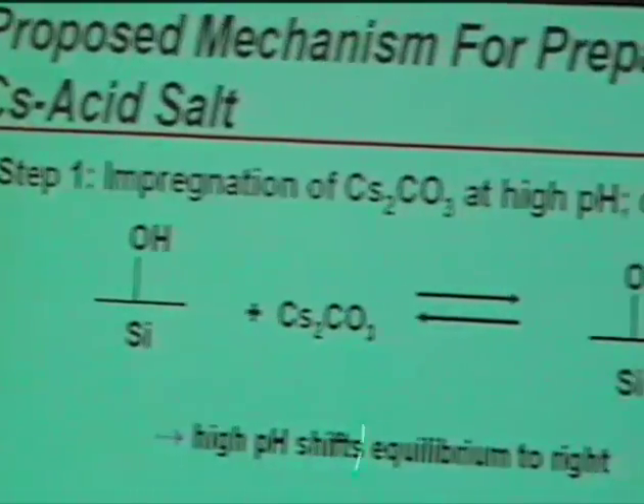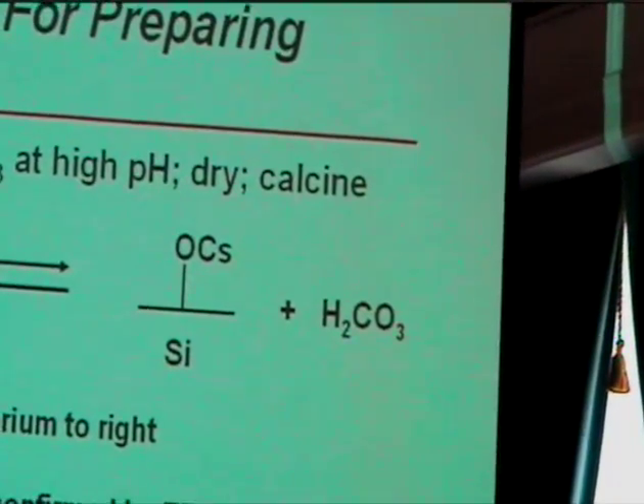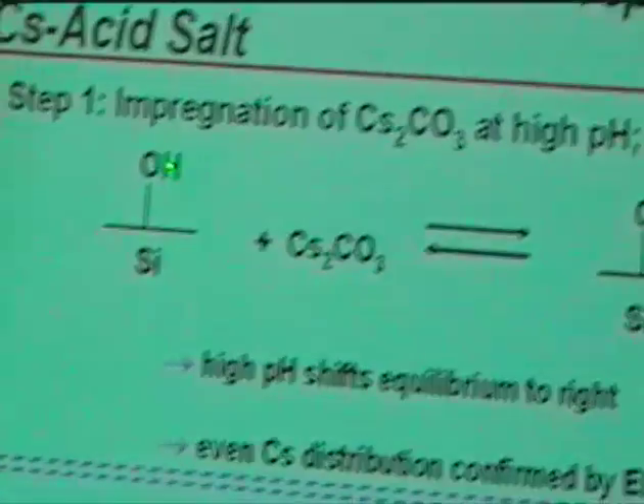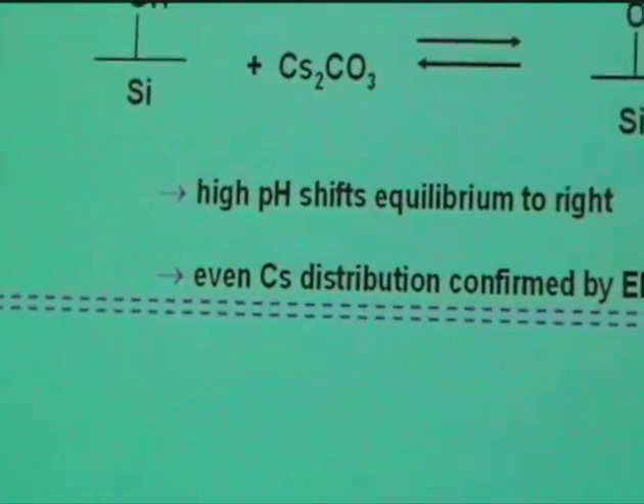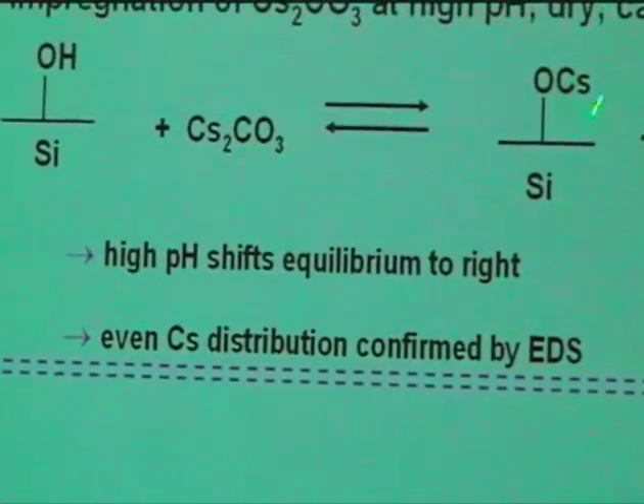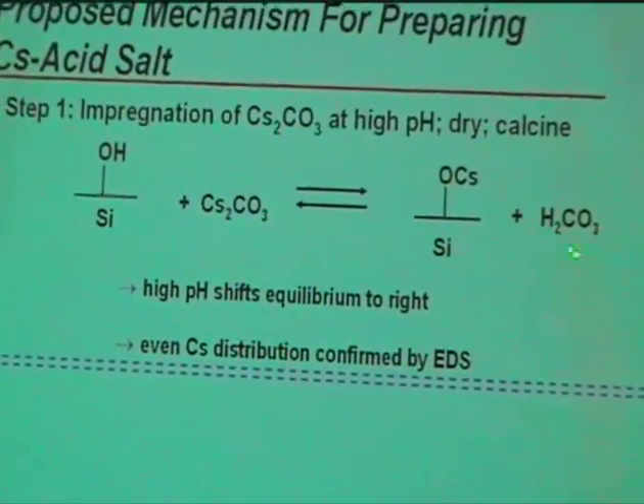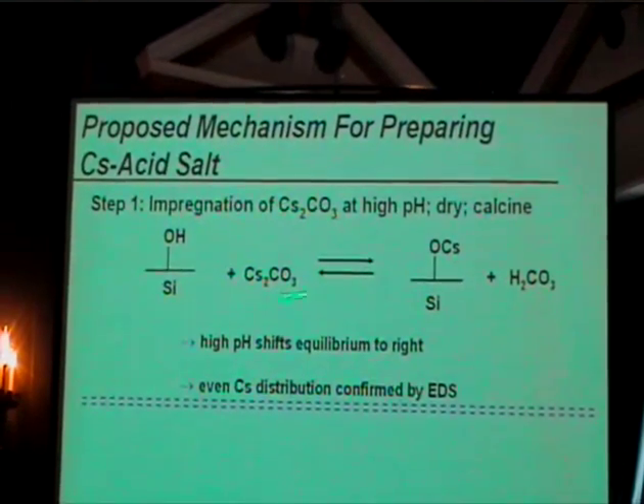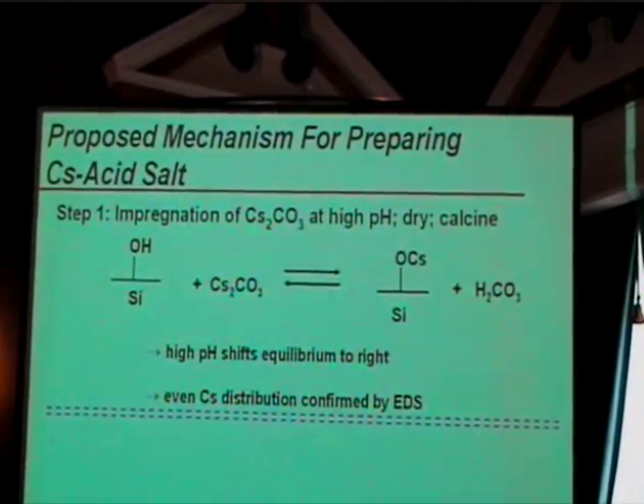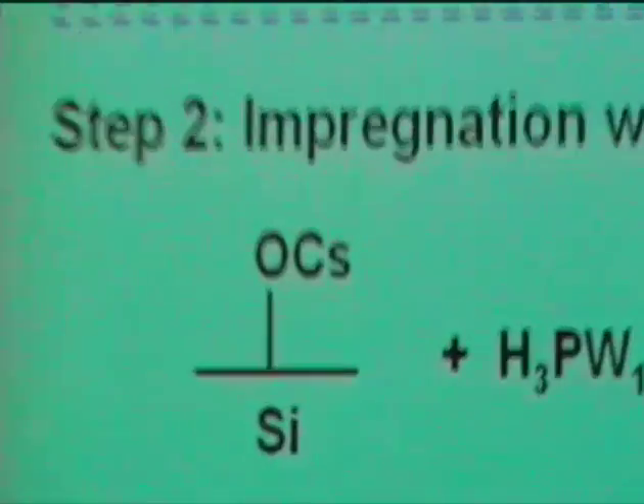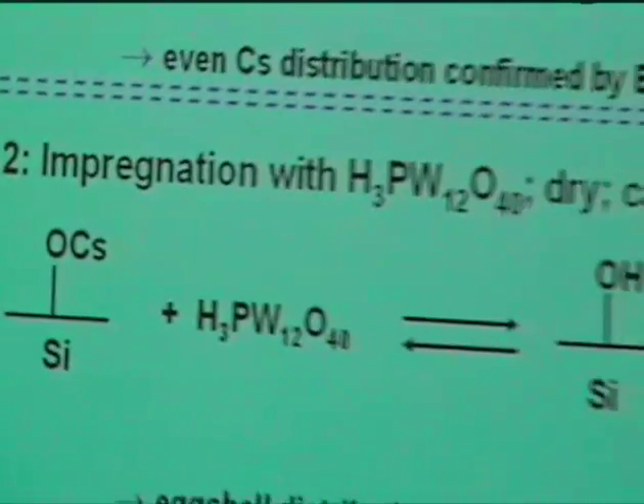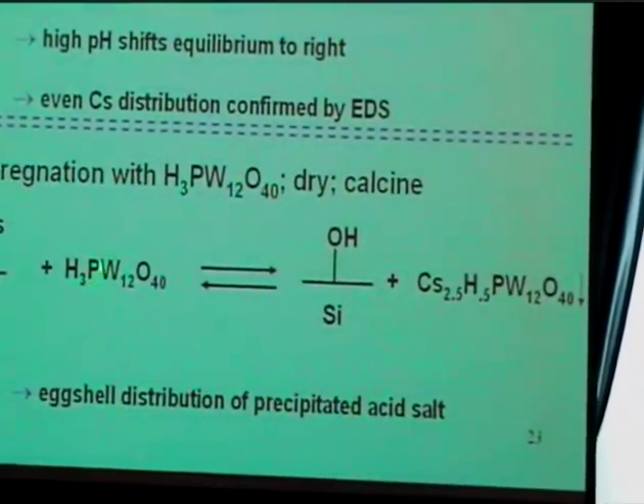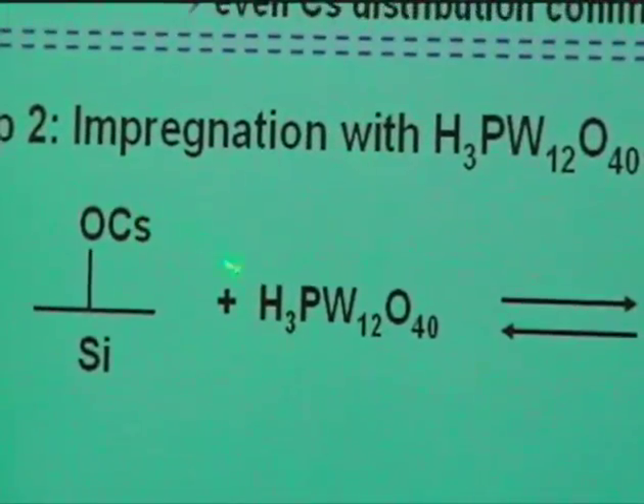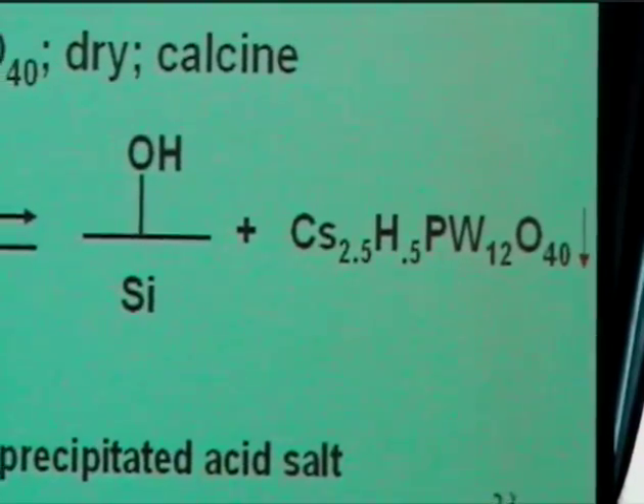So this is in fact what happened. We have a silica surface. At high pH, what we first did was impregnate with the cesium carbonate. Now when you do that, you get an exchange. The proton is exchanged with the cesium when you do this at high pH. So you wind up decorating the surface in a very even mode all throughout the extrudate with something that looked like this. Carbon dioxide goes away as this, and you basically had the surface set up. Now when you come in with the phosphotungstic acid, you're doing this at low pH now, the reverse exchange happens. As this starts to impregnate through the outside of the extrudate, you start getting some exchange of the cesium into this H3 salt.